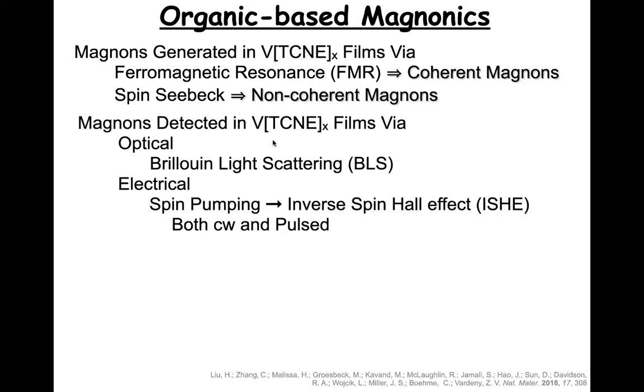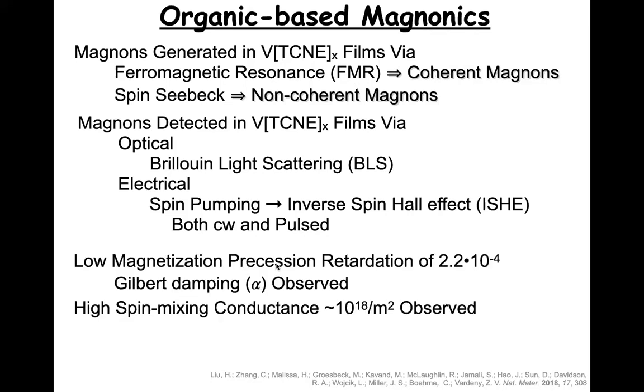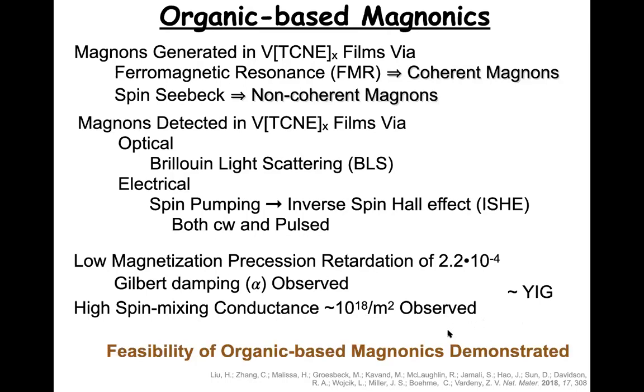And we can also detect them optically by Brillouin light scattering, and spin pumping, detecting by the inverse spin Hall effect. Both work with CW and pulsed lasers. And the Gilbert damping is 2.2, which is very comparable to 2.1 times 10 to the minus 4 compared to YIG. And the spin mixing coefficient is very respectable too. So in fact, we have demonstrated organic-based magnonics using our films of vanadium TCNE. The feasibility of this obviously has been demonstrated.